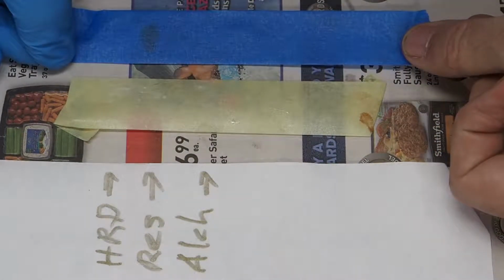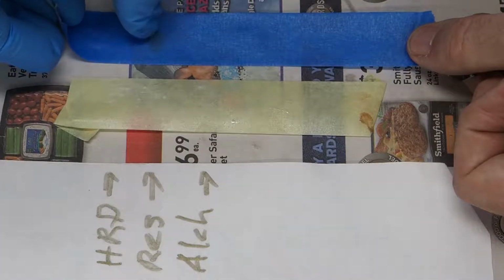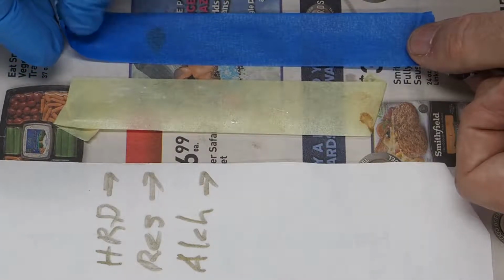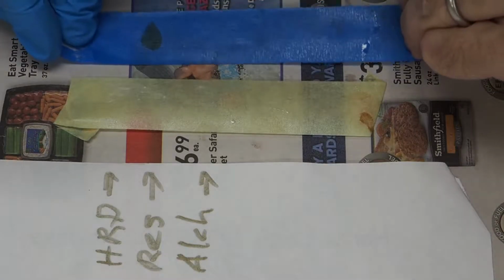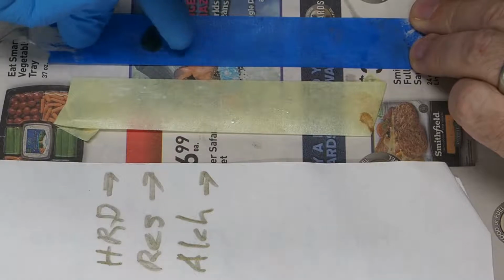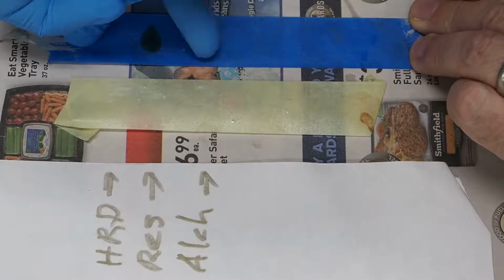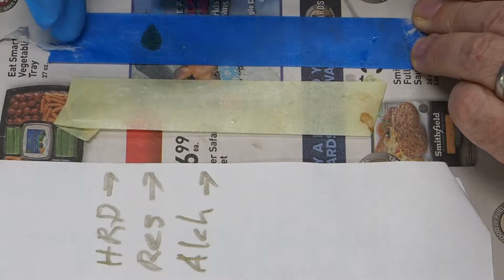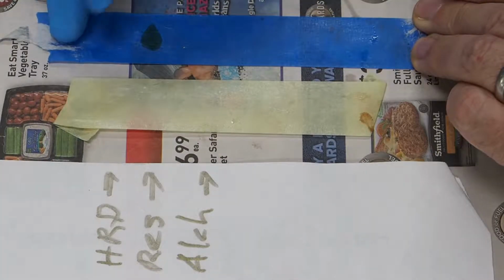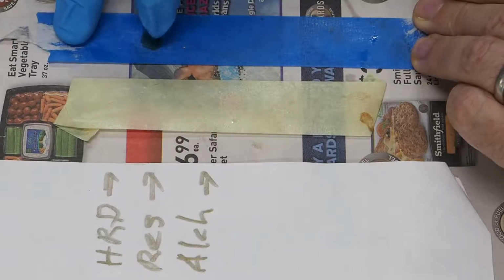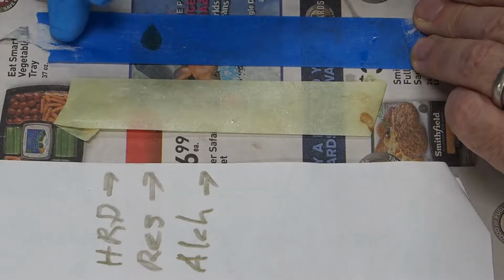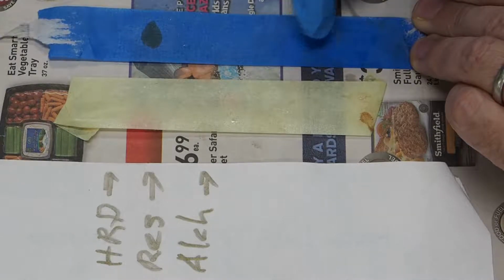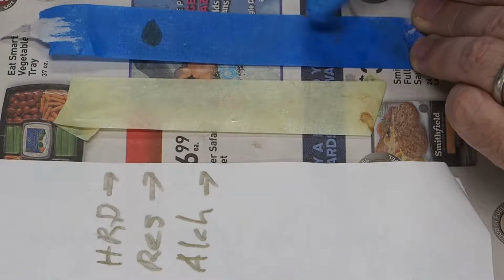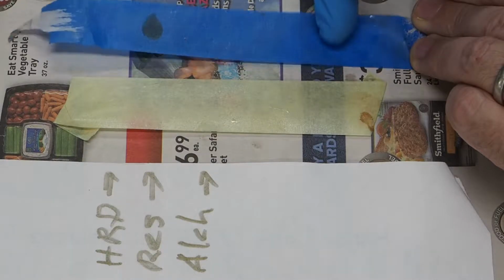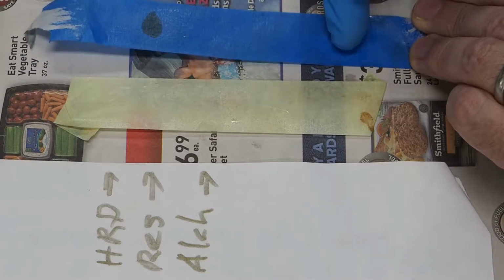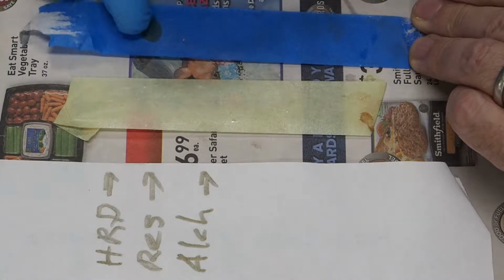So it did discolor it on this painter's tape. So it soaked into at least the far surface. If you look at the backside of a piece of tape where the adhesive is, there's kind of a graininess to that adhesive. I can see that the graininess still appears to be present where the hardener was. If I come down here where the acetone was, I can see that where I wiped it, it actually came off. So acetone removed the graininess, which means it removed the adhesive down here. Here I can still see the adhesive.